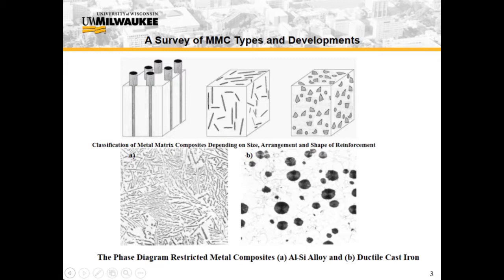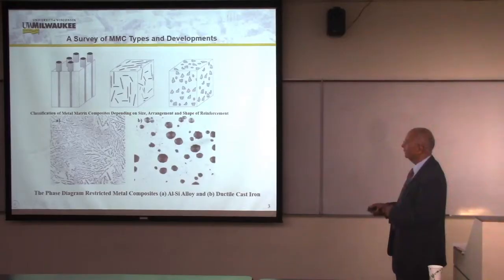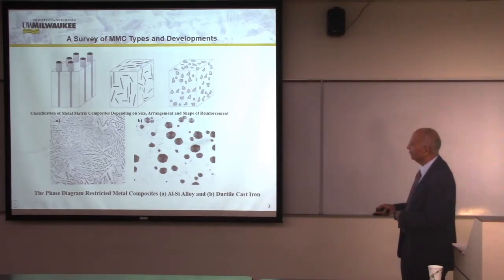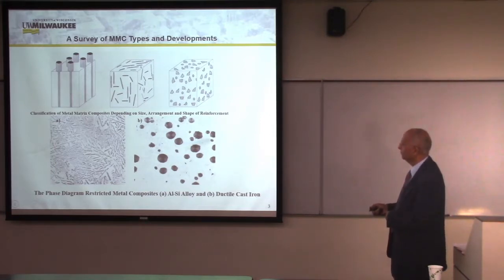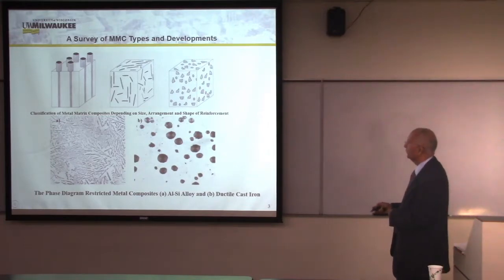composites. The foundry industries have been producing cast metal matrix composites for a very long time. And examples here are this aluminum silicon eutectic. Silicon needles dispersed in the matrix of aluminum, and ductile iron, which is graphite nodules dispersed in the matrix of iron. Both of these are extensively used in the automotive industry, and many of you who have driven today to the conference probably have components both of aluminum silicon alloys and ductile iron in the cars that you drove to this meeting.